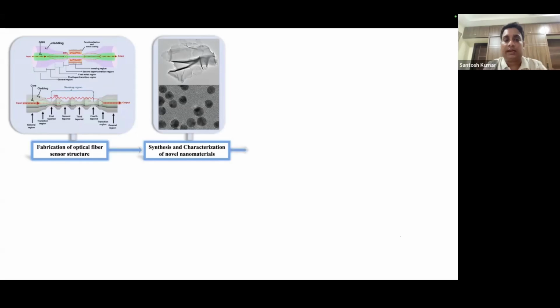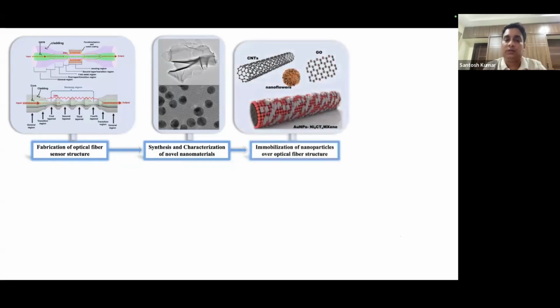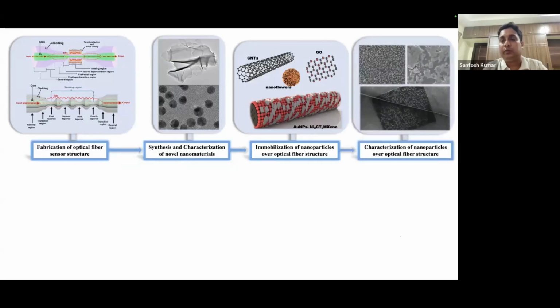So after synthesis we do the characterization using TEM, STEM, SEM, some AFM and FTIR, and we do several characterizations before use. After characterization we do the coating of these nanoparticles on the optical fiber. This is not easy, so I will discuss the coating process in detail. After coating of the nanoparticles, we again do characterization of the nanoparticle coated fiber structure using SEM, and through that we verify whether all the nanoparticles are immobilized on the fiber structure or not. And then to confirm the material composition we also do SEM EDX.